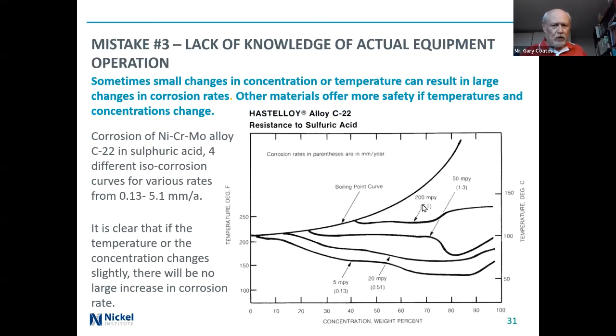This is an iso-corrosion curve for sulfuric acid. It's for the C22 alloy. And there you can see here, it's 5 mils per year, 0.13 millimeter per year. And you can see that a 5 degrees C increase in temperature will not mean a lot. 10 degrees C might mean a little bit more, but still it doesn't corrode as quickly as the duplex alloy with the same change of temperature or concentration. So I like to see curves like this, so that it gives me more confidence that if an upset occurs, the material is not going to start corroding very, very quickly.